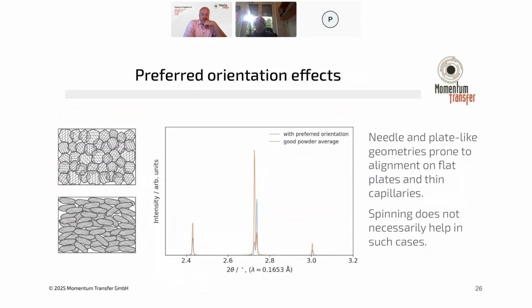So just a further point on this preferred orientation, if you look on the left-hand side, I have two images here. One has more spherical looking particles, and in an ideal powder, you want to measure all of your different crystallites and particles statistically in all directions so that you collect a spherical average of your diffraction signal in all directions. But what can happen sometimes if you have needle-like or plate-like morphologies is that these particles can start to stack up in a way where they're all aligned along the same direction. And if you have this, which is called preferred orientation, it can significantly impact the relative intensities of the peaks in your signal. So if you know what the structure is, you can correct for that in a refinement. However, sometimes this can cause issues with identification, and it can also decrease the accuracy of quantitative analysis as well.